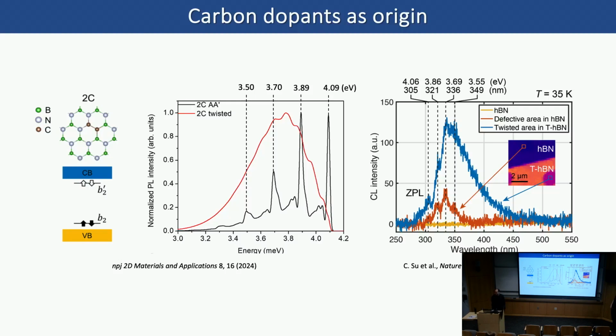You mentioned the single photon emitters in defected monolayer boron nitride. Do you expect the twisted bilayer boron nitride to have the same single photon emission? I don't know if there was any data on that either. Well, what we showed for those twisted hBN are two bulk hBN twisted to each other. Oh, I see. So those are not bilayer twisted. Right. But we would definitely like to see if a bilayer hBN could reproduce some of our observations in those bulk materials.